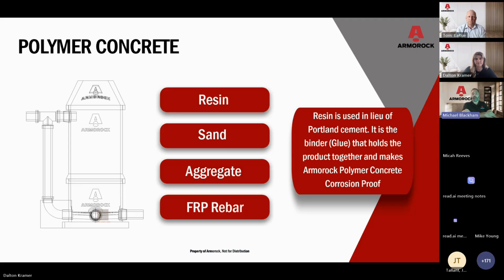Another benefit of Armorock's polymer concrete specifically is the use of fiberglass reinforcement, or FRP, instead of your conventional steel reinforcing. Not all polymer uses FRP reinforcing, but at Armorock, we really think it's important, by eliminating that typical steel reinforcing in our manhole structures and using the FRP to achieve a fully 100% corrosion-proof design.